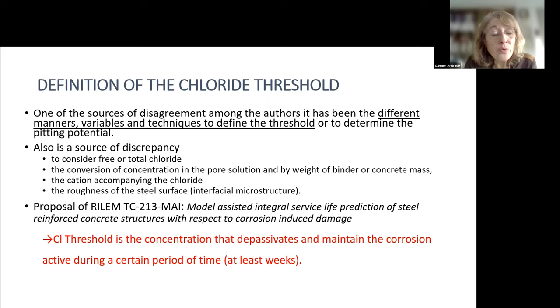We defined it for the sake of the committee, but we didn't express it especially for the rest, because we thought that it was clear enough. But we define it, and I think that this is in agreement with what Rob has presented, that the chloride threshold is the concentration that depassivates and maintains the corrosion active during a certain period of time, at least weeks. That means that, as Rob has presented, you may have an activation, but also Federica showed that it might be repassivated or the corrosion may not progress. And only when you have permanent active corrosion may you be sure that this is the depassivation threshold. We define it in this manner, and I think it's very important that for the future we agree and we publish a definition of the chloride threshold.